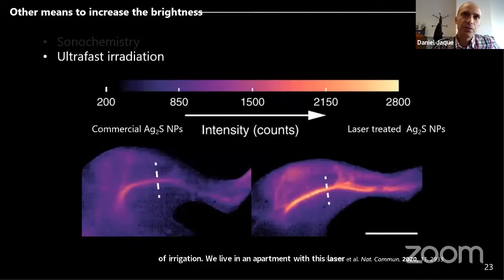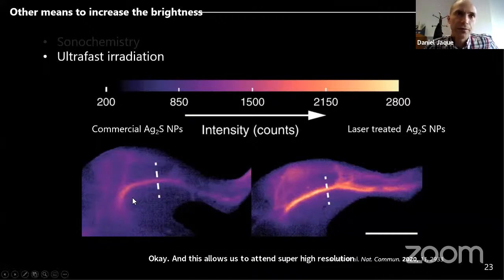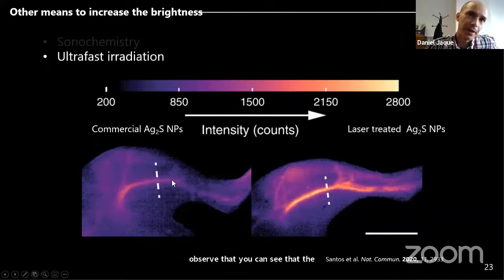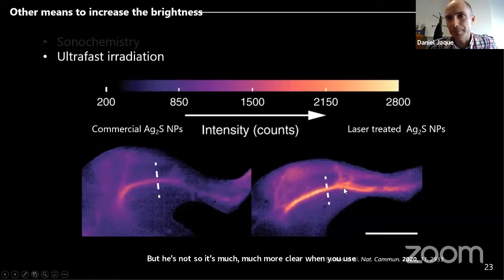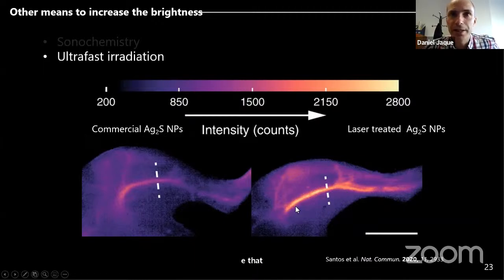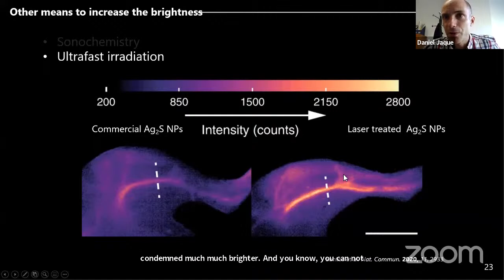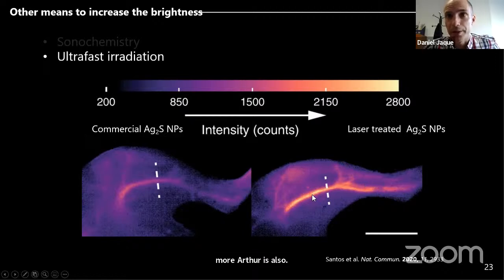Okay, and this allows us to obtain super high resolution of, for example, the vascular system. This is an image of the femoral artery after injection of silver sulfide nanoparticles, obtained with the commercial silver sulfide nanoparticles. You can see that the artery is visible, but it's not so clear. It's much more clear when you use this laser-treated silver sulfide nanoparticle because they are much brighter, and you can not only see the femoral artery, but you can see also the small arteries, and also here you can see the bone because the nanoparticles are also accumulated at the bone.